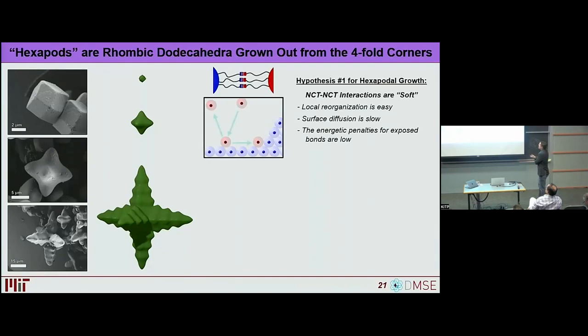The first is that these hexapods grow because our NCTs are soft. So compared to, say, a hard-packed sphere, a soft sphere, if it lands on a crystal at a site that is near to where it should be in terms of binding and forming part of the crystal, it can very easily just sort of bend or stretch the polymer chains to be able to accommodate it. So it very quickly wiggles into place. The flip side of that is that even though there's a very rapid reorganization into sort of a nice continuation of epitaxial growth, there's not a strong driving force for it to diffuse all the way across the crystal to go to a lower energy site, because the polymer chains are already accommodating that. So we don't really have an easy way to get these things to grow into a nice, large Wulff polyhedron, because the driving force just isn't there.